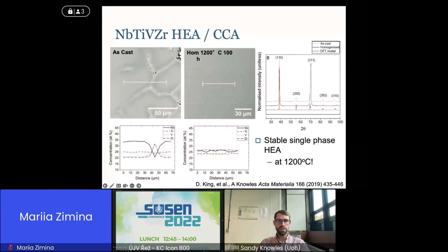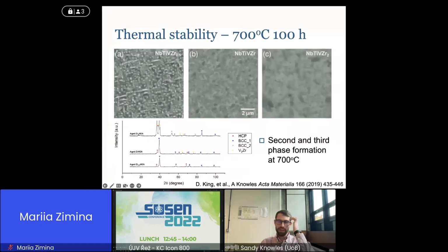So in this system, we did find that these niobium, titanium, vanadium, zirconium high entropy alloys are single phase stable at 1200. So they do meet this criterion of being a high entropy alloy. So there is potentially some entropic stabilization involved. However, going towards reactor operating temperatures, at 700 degrees C you get precipitation and the forming of second or third phases. Depending on the composition, the zirconium concentration, we got differences in microstructure. So we got some spinodal, some HCP formation, as well as Laves phase formation.